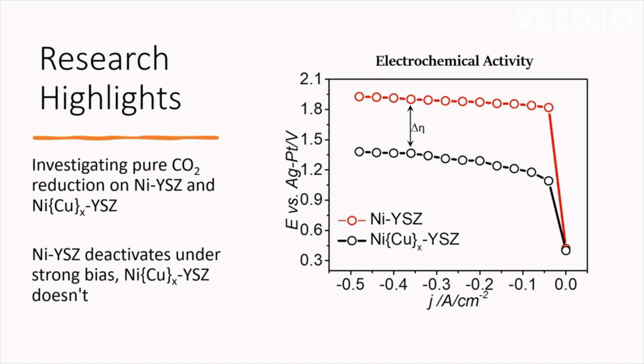To understand why the electrode breaks down and to mitigate this problem, we infiltrate the nickel YSZ electrode with copper. And we found that infiltration of copper, as we can see here, significantly reduced the cell overpotential and it does not break down. So to understand why the nickel YSZ breaks down while nickel copper does not, we carried out Operando Raman studies.